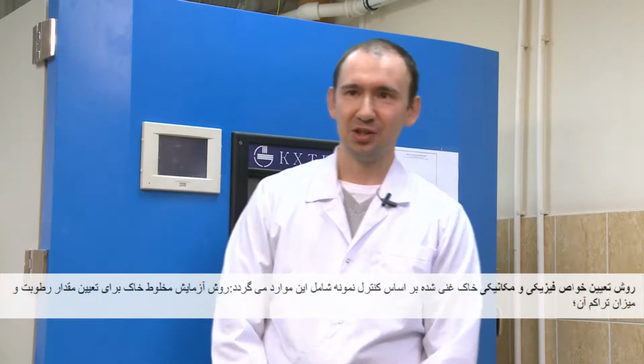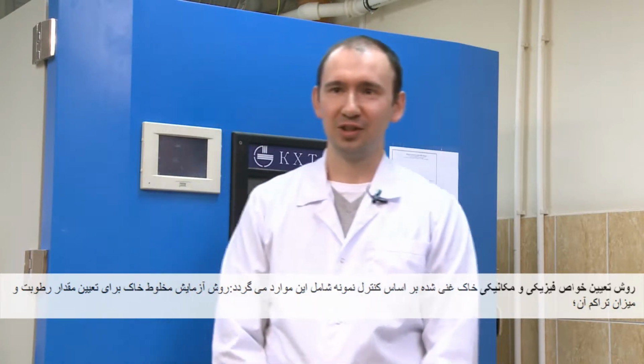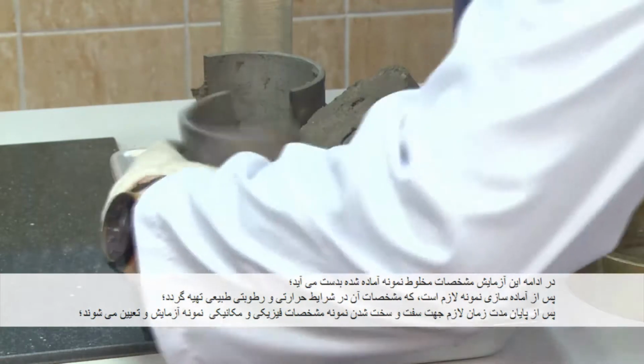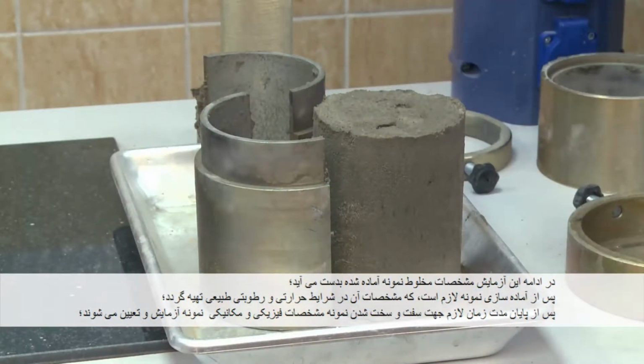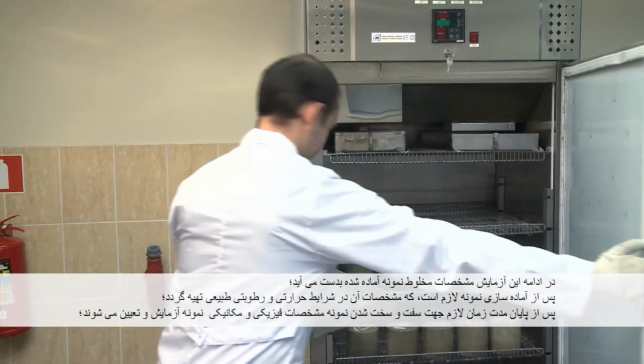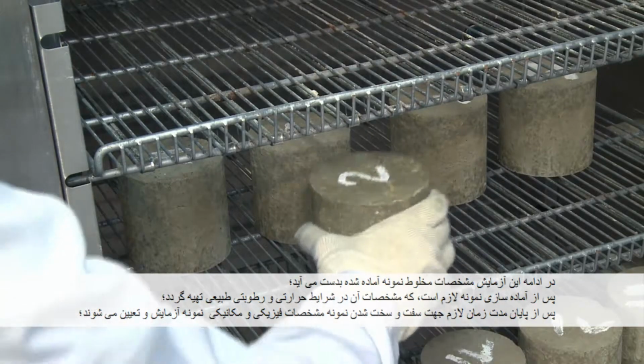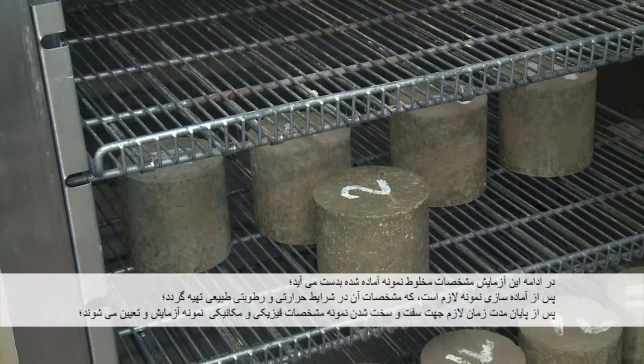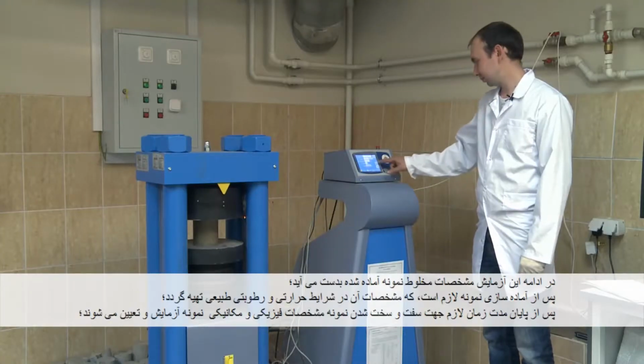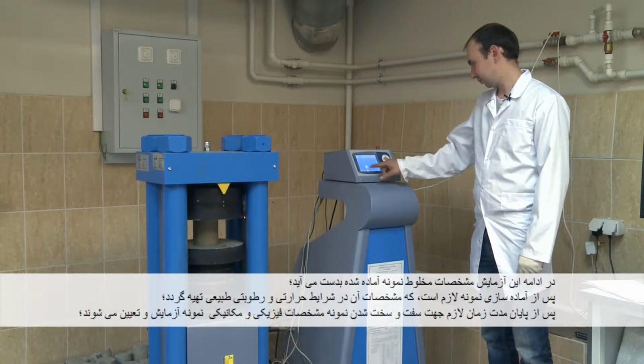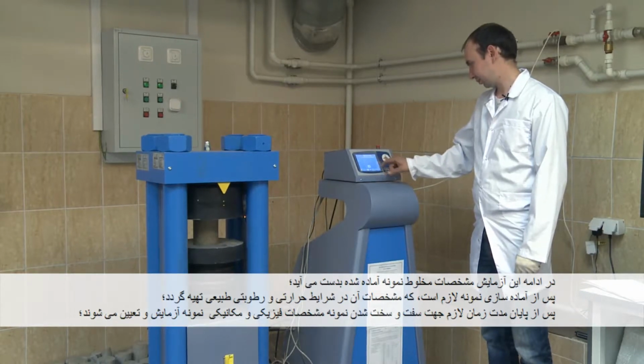The procedure for determination of physical and mechanical parameters of improved soil using reference samples includes testing the mixture to determine its optimum humidity and maximum density. After that, samples are prepared using the obtained mixture characteristics. After manufacturing samples, it's necessary to provide their storage at normal thermal and humidity conditions. After the standard curing period is over, samples are tested and their physical and mechanical characteristics are determined.